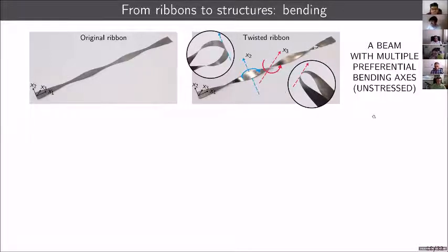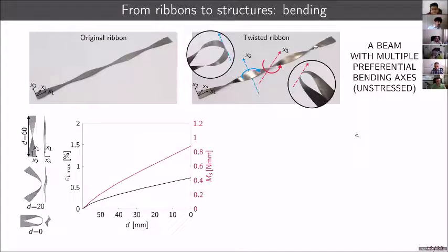We also did some numerics on this bending process to make sure that we were not exceeding the elastic limit of the material. And what you see over here is the bending behavior of one of the thin necks. So we take a smaller region of the ribbon and we bend it. Here we're plotting the maximum principal strain versus D, which is basically a function of the bending angle. And we can see that the strains do not exceed the 2% limit that we imposed.